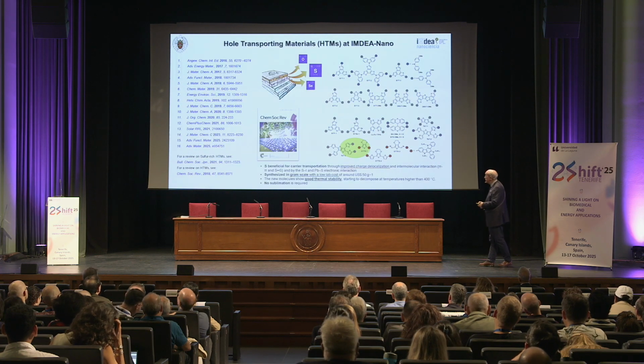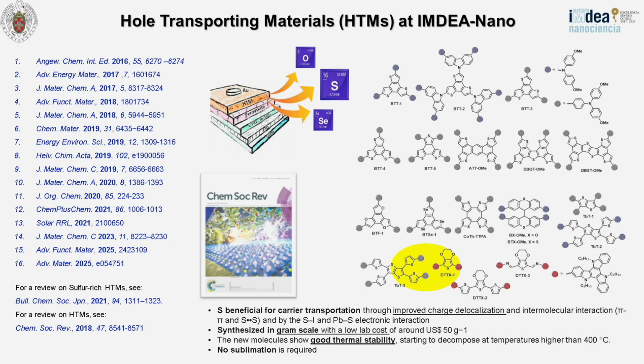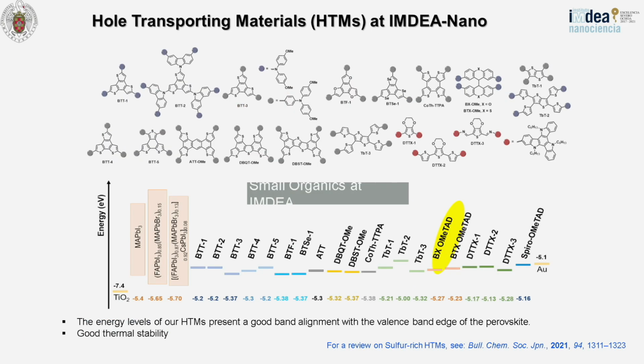Okay. In this slide, there are most of the papers we have reported on hole transporting materials. All of them are based on chalcogenides: oxygen, sulfur, selenium. This is because of the beneficial interaction of these elements and the size of sulfur and selenium as well. So let me give you just a couple of examples of these systems. And you see that in all of the molecules we synthesized, there is a perfect alignment with the spiro.